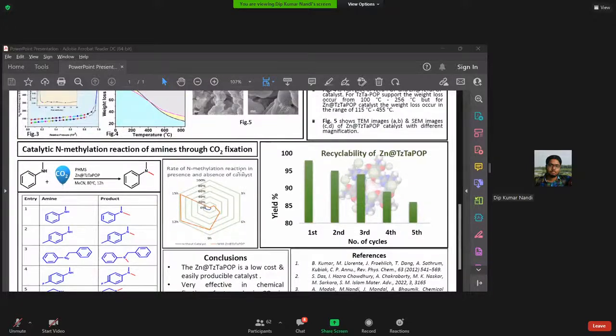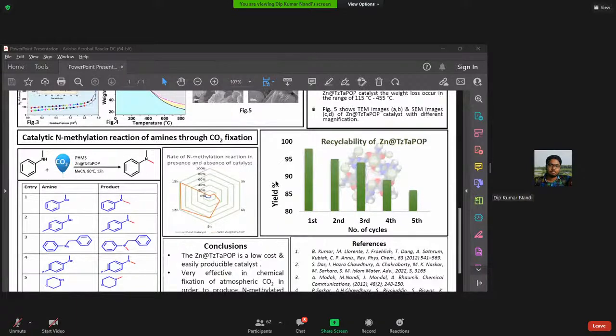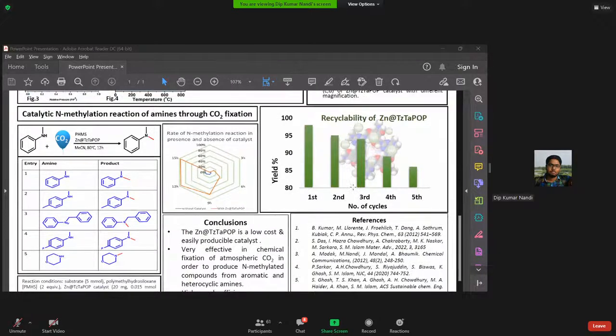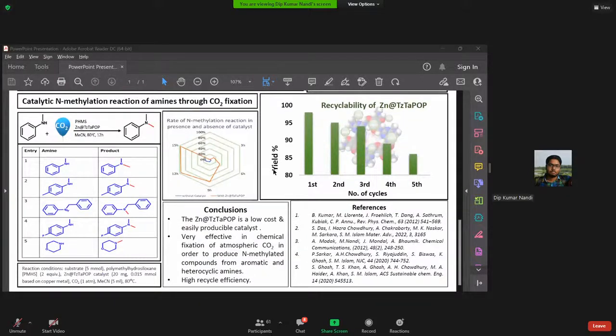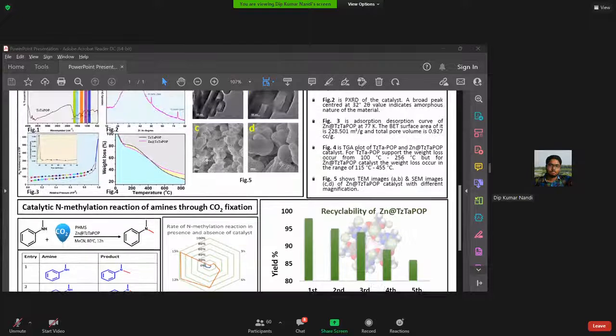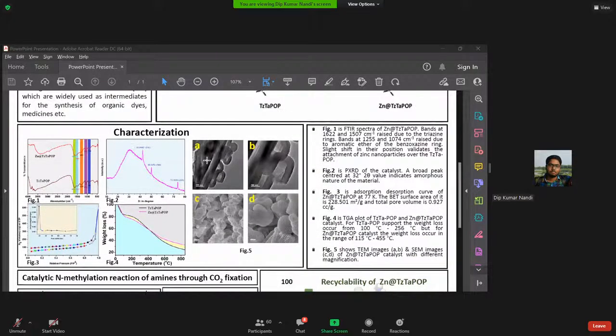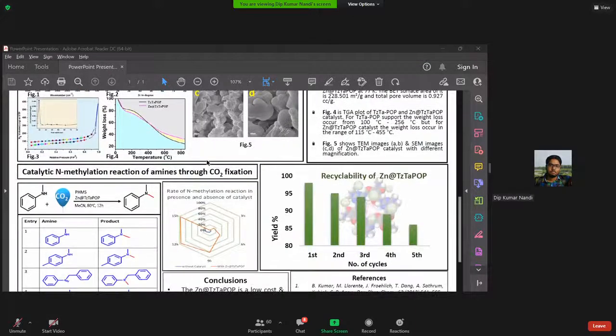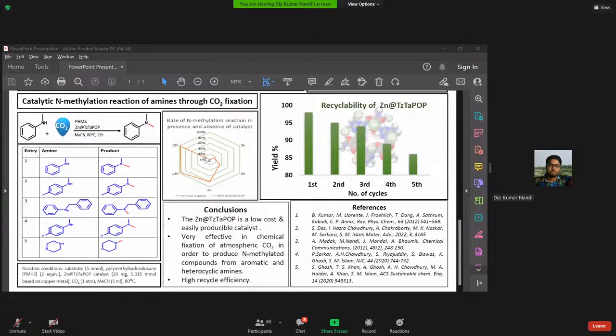And the more interesting thing is that it is very recyclable. We used this catalyst for 5 consecutive times, and we saw that the yield decreases slightly, but it is not very low. Again, we did the reaction with and without catalyst. After 15 hours, there is almost 98% yield, but without catalyst, the yield percentage is very low. From this, we just showed one reaction for chemical utilization of CO2, but we can do carbamate formation and other CO2 fixation reactions. So we can conclude that this is a very efficient recyclable catalyst from which various types of CO2 fixation reactions can be done.